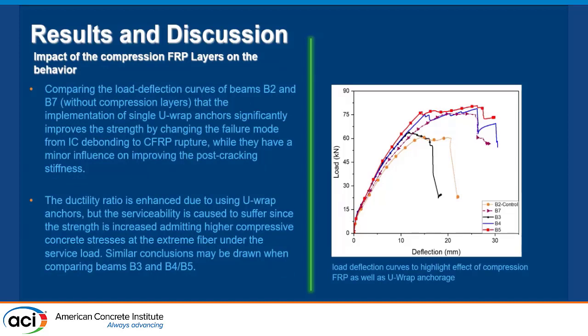So comparing the load deflection curve for B2 and B7, we can see here the impact of the compression FRP layer on the behavior. We can see the implementation of a single U-wrap just improves the strength by changing the failure mode from the debonding to the FRP rupture, and it has a minor influence in improving the post-cracking stiffness.